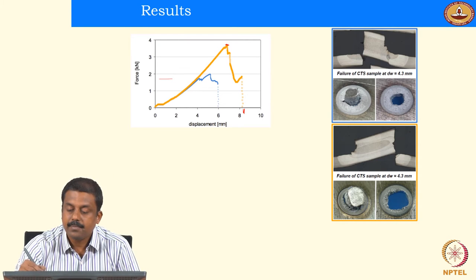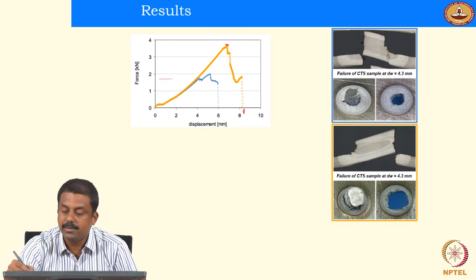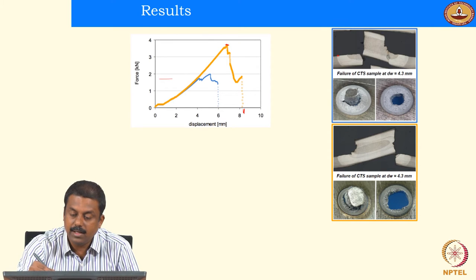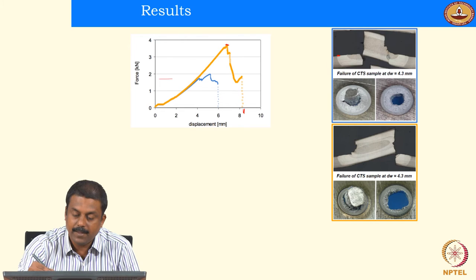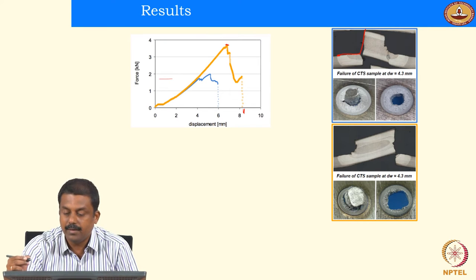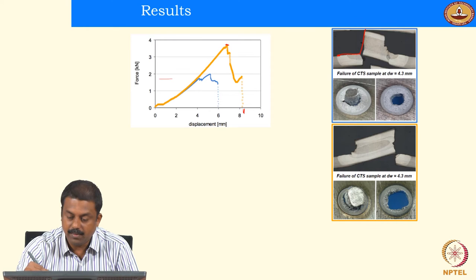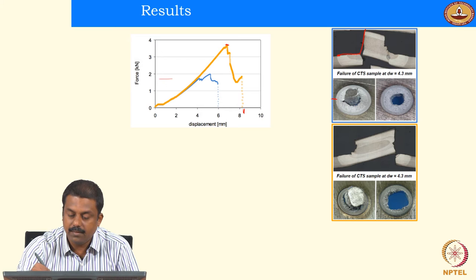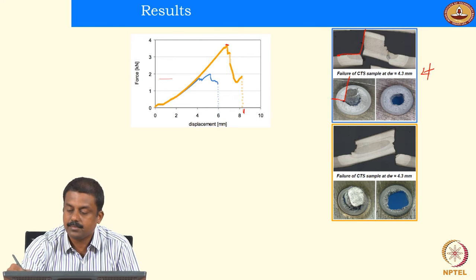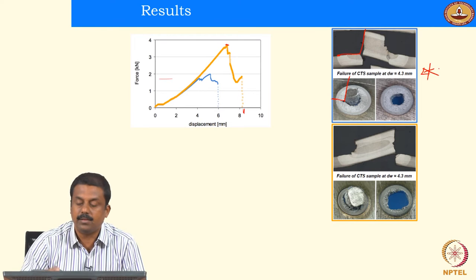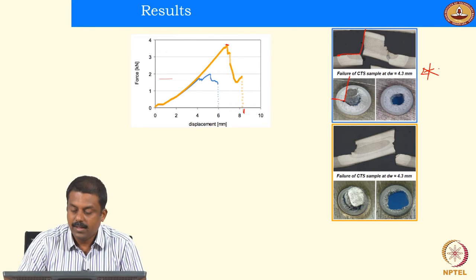So you will see in the first pulsing case, the blue case, the failure nucleated at the interface from the heat affected zone, and then it propagated along the weld center line, and then the failure of the plug happened in a partial plug mode. So the crack propagated, and then it broke at the middle of the weld nugget, and this is not an advisable failure mode because you have a plug failure.